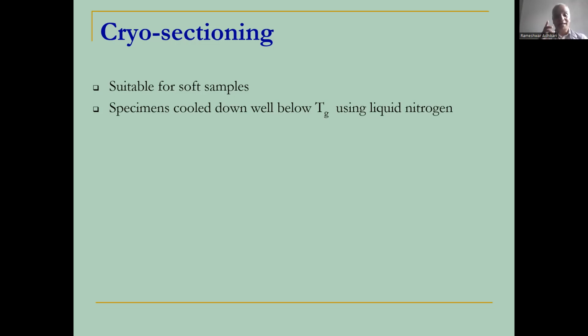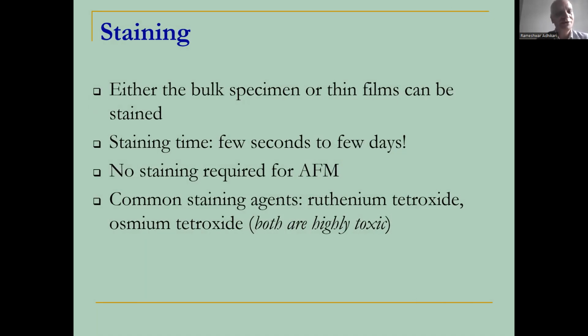Anyway, in that case, what we have to do is think of cooling the sample so that the sample becomes glass or glass-like. And in that case, we have to cool the sample below the glass transition temperature, so-called Tg, of the polymer. That we do, and we do cryo sectioning. We do the sectioning not at room temperature, but at lower temperature. Of course, we have to devise the microtome, ultramicrotome, in a similar way.